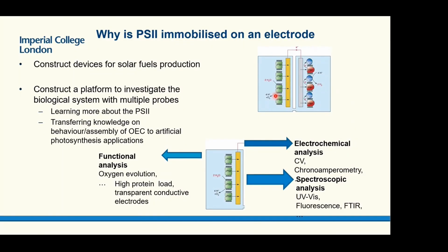These reactions, especially the oxidation of water and the charge separation event, can lead to the formation of reactive oxygen species that damage the protein, so the lifetime of the protein is only half an hour. So it's quite difficult to make a system that is long-lived. But instead, we could think about having a system that is vectorialized.